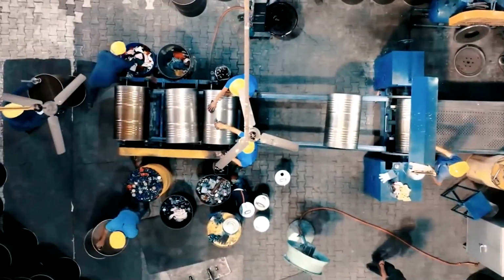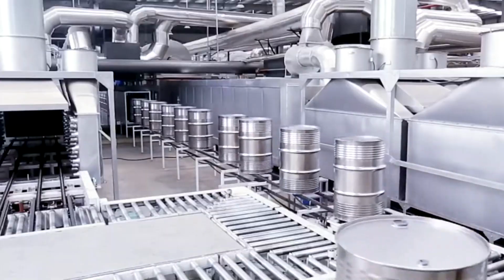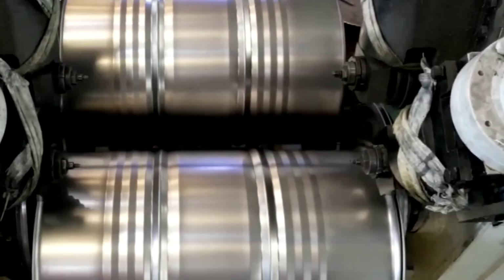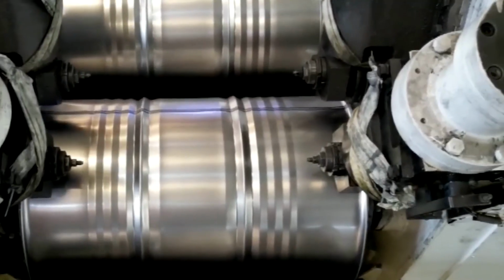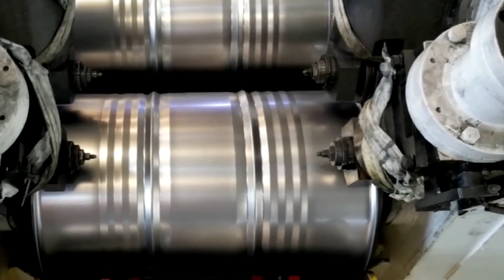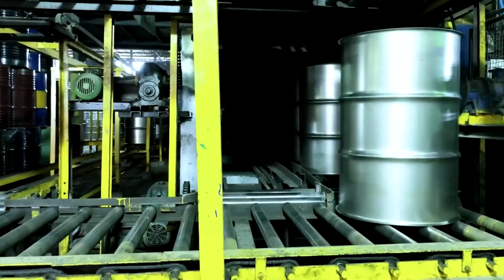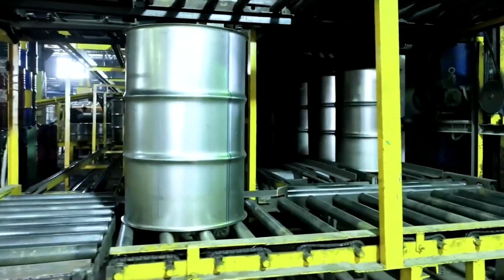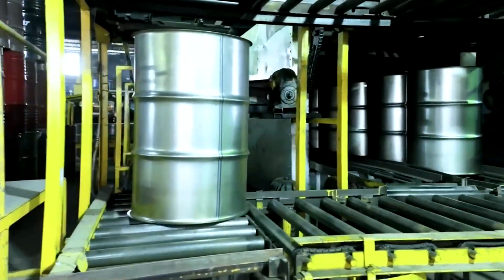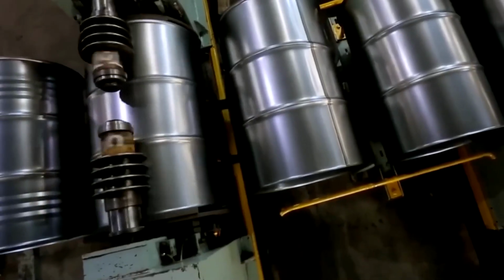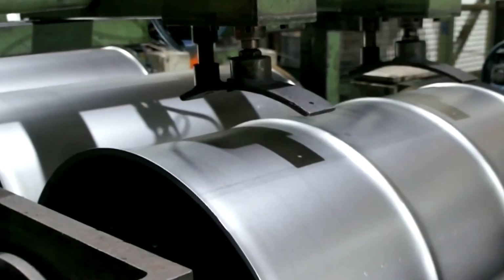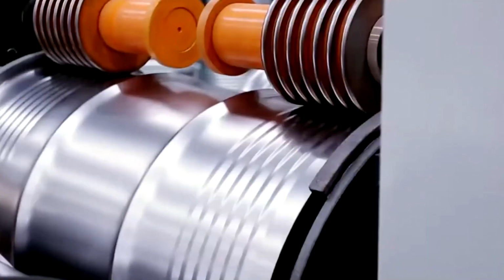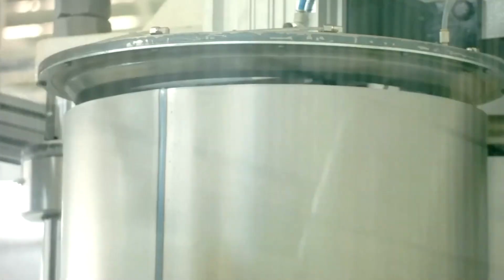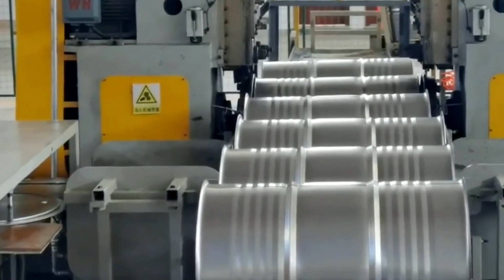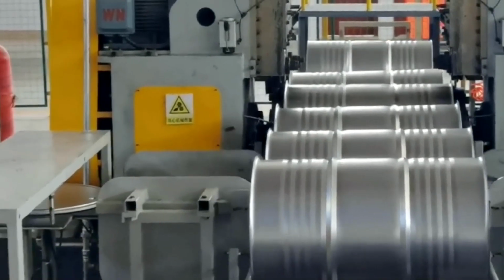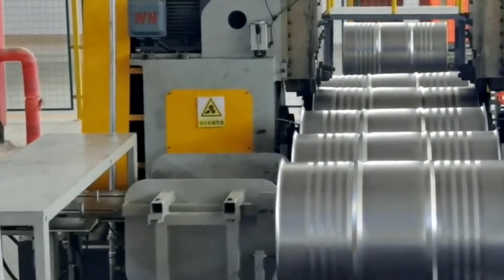The process is only gaining momentum. One can notice how the drum body remains perfectly stable, while the specialized rollers apply constant force to the central section of the steel. This ensures that every raised rib maintains a uniform depth of several millimeters and consistent spacing around the entire 360-degree circumference. Every position and the exact distance between these ribs is calculated in advance by engineers to distribute internal forces and external stacking loads. But this is just the beginning.